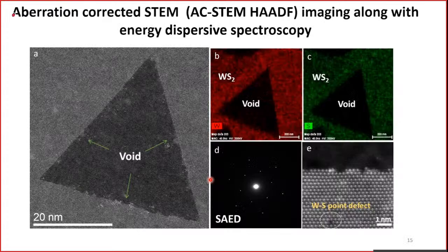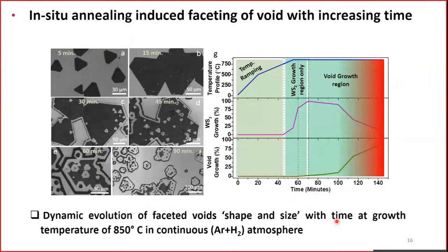I'll show you how we know it is a void, and how we know the termination. We use an aberration corrected microscope, in this case STEM in HAADF mode. We can see these are your tungsten and sulfur. Of course, sulfur atoms are not visible in this image. We can clearly see a void here. And again, by EDS mapping, we can confirm it is a void. We can also clearly see in a high magnification image there is a point defect. So these are the defects. When we have more and more of these defects, they cluster together and contribute to the formation of faceted voids.